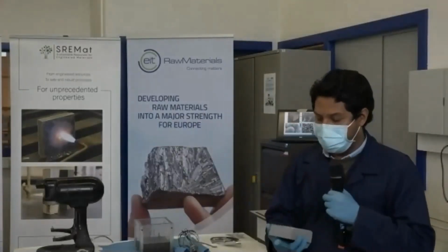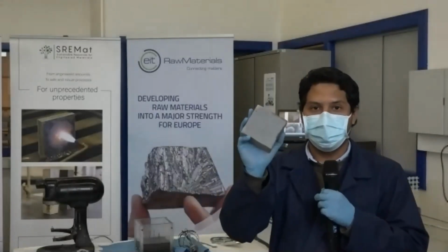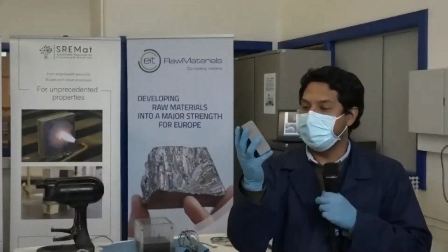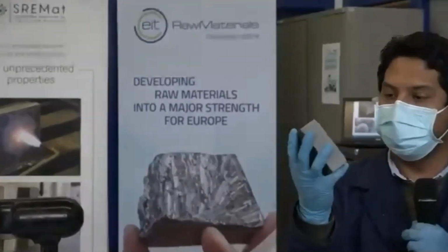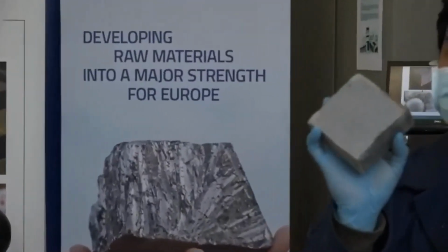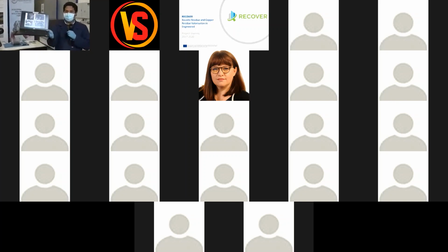If we take that and then we put it, for instance, into hydrothermal conditions, we will end up with something like this. As you can see, it changes the color. It changes the color because of the processing of the material, but also because you are forming different things inside of the pores of this material. Normally, what you will form inside of these materials is this. Inside of those pores, then you will create also different crystals, as you can see in those pictures. And these crystals normally will help us to have different properties.